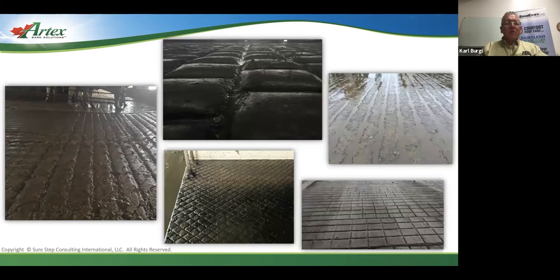The next thing here is you see this type of flooring, one that eroded really quickly because it was probably poured during hot weather and not covered up. This was only about 3 years after it was built. The whole breezeway, the whole travel lane was like that. They covered some of it with rubber, but the rubber was eaten away after 3 or 4 years from the bottom up because the surface underneath it was too rough.